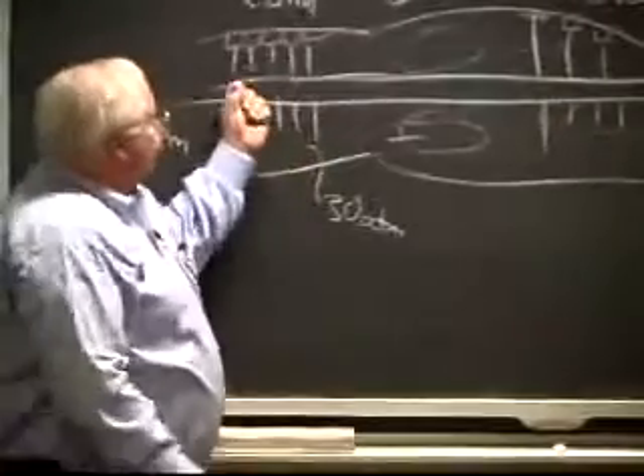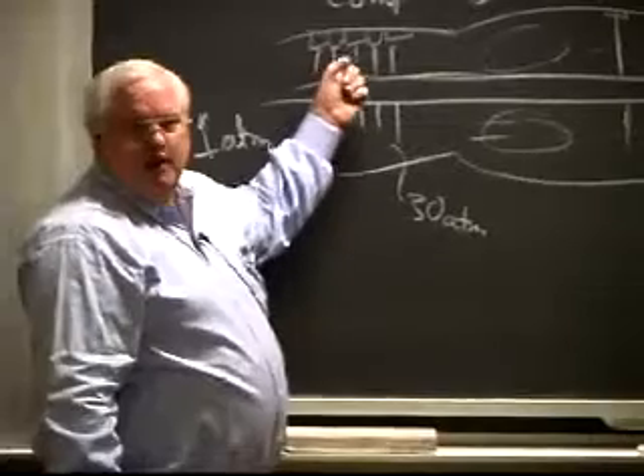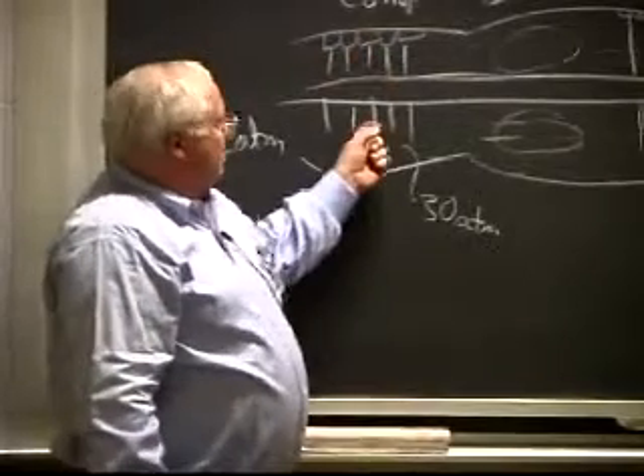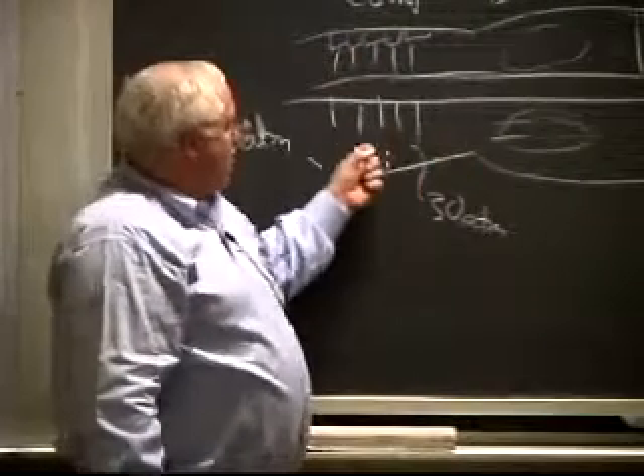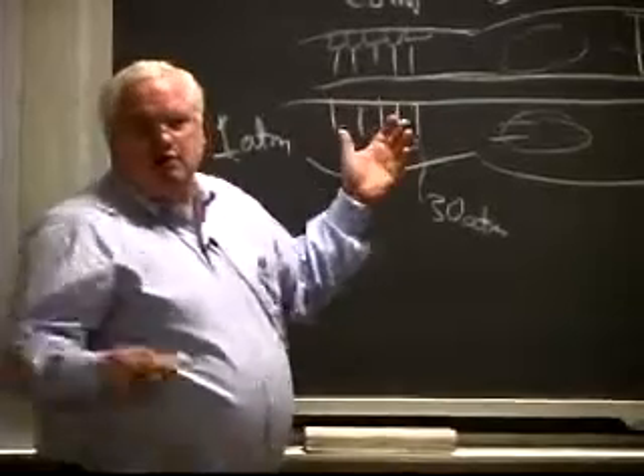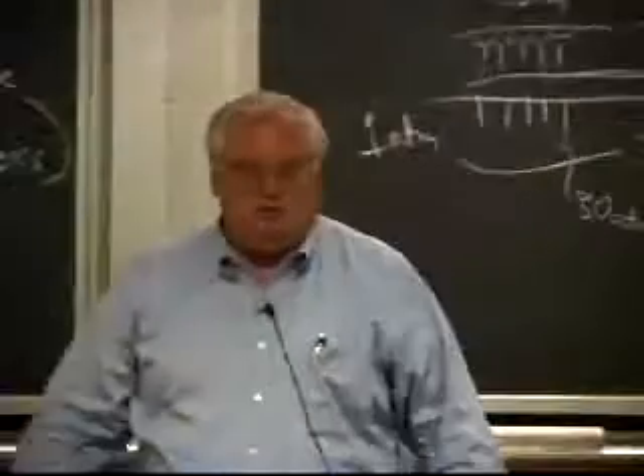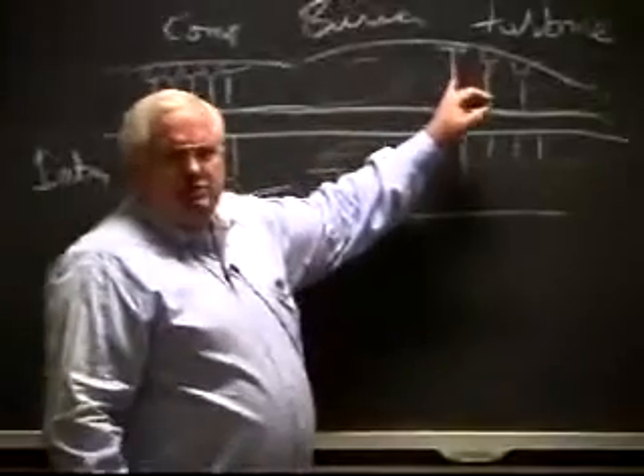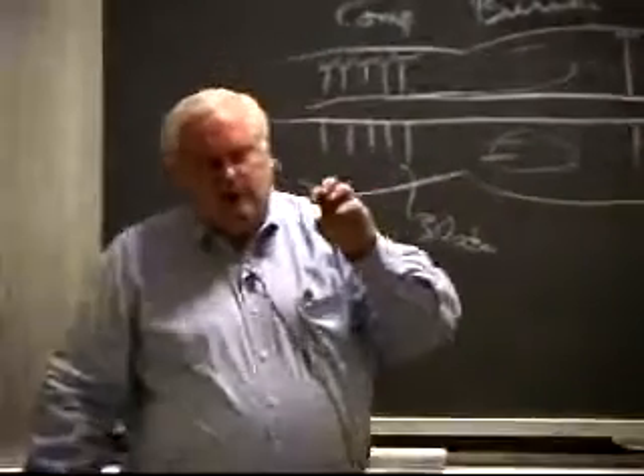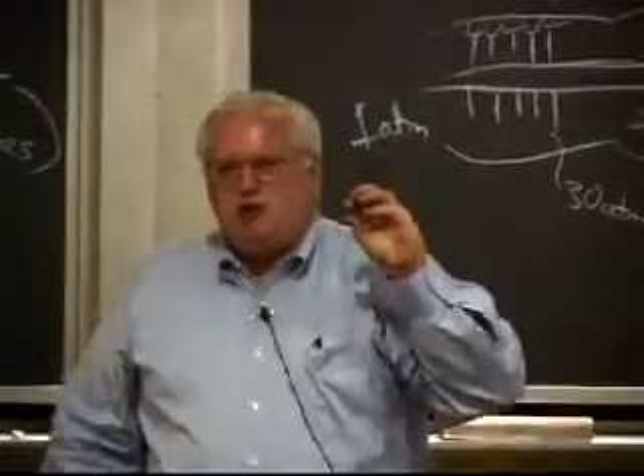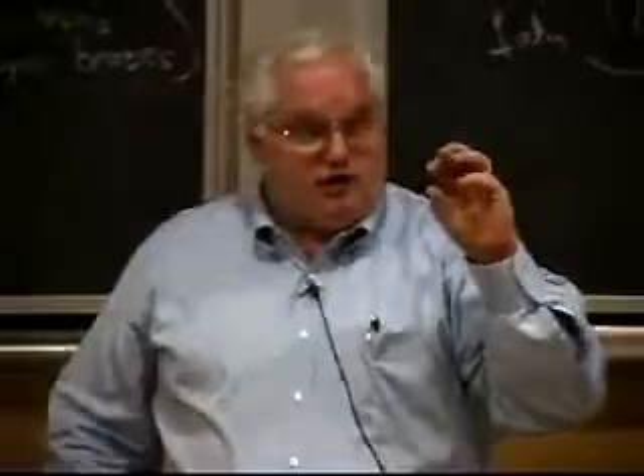the reason you need a seal is because this is nothing more than a fan, and if you didn't have a seal, you've got a higher pressure here than there, and you'd have backflow, and that can degrade the efficiency of the turbine. You can have a big degradation in the efficiency of the turbine, 10% or more if you're not careful. If you want to get those last few percent out of a turbine or a compressor, you want to put seals in here. One type of seal is to take thin nickel-based superalloy foil, this would be foil like 2/1000 of an inch thick, and make a honeycomb structure.